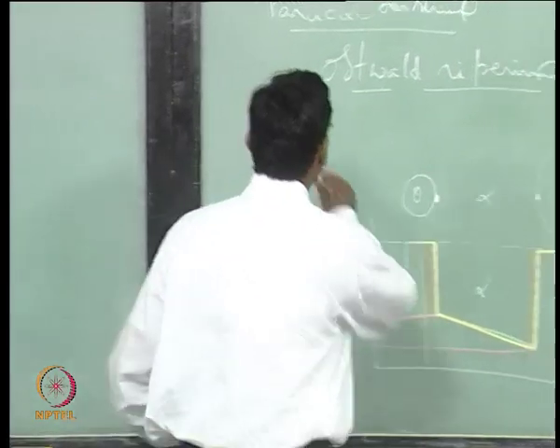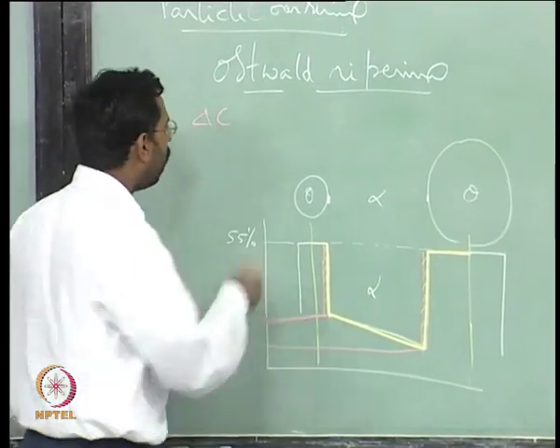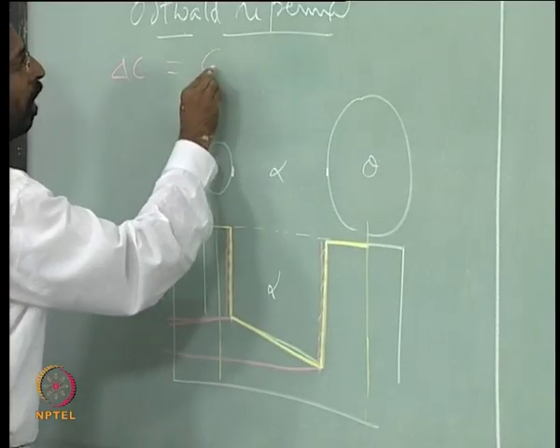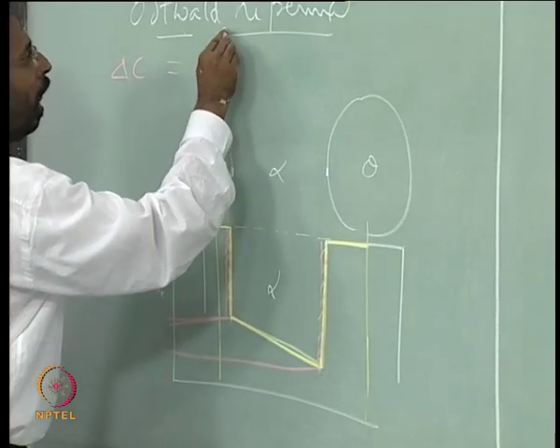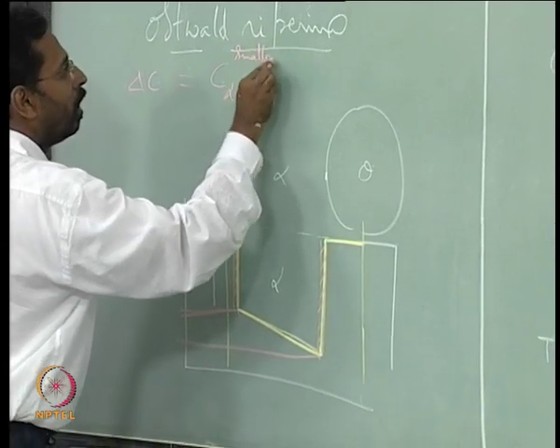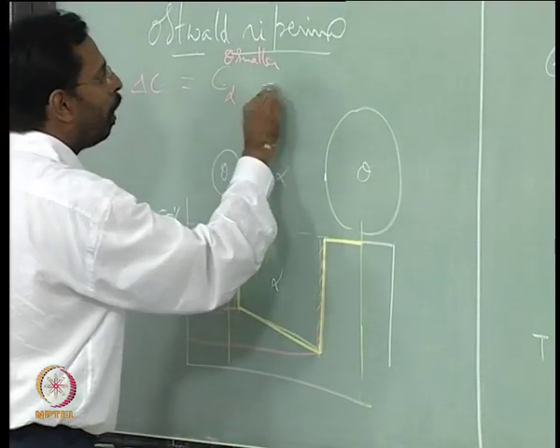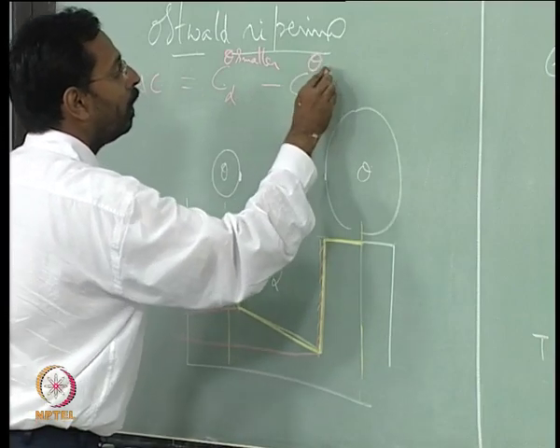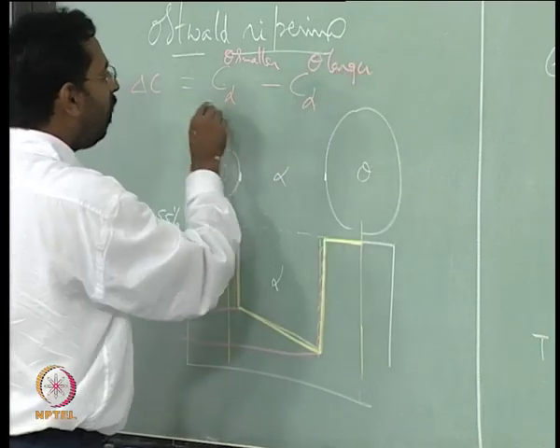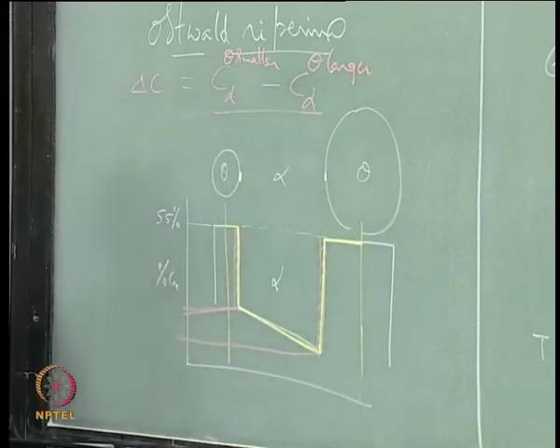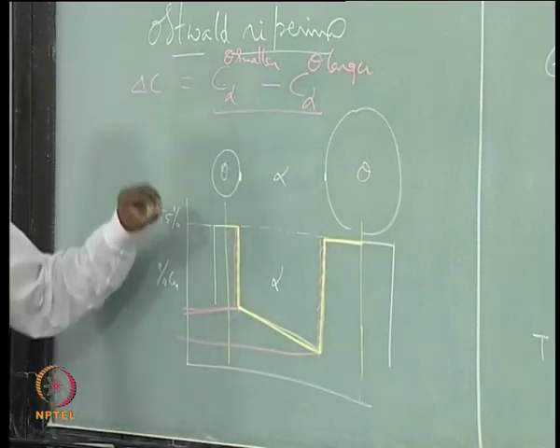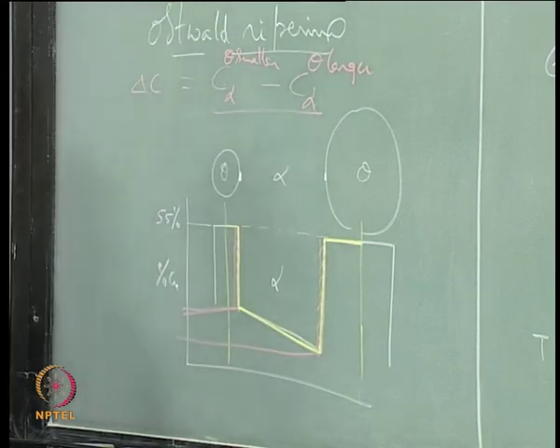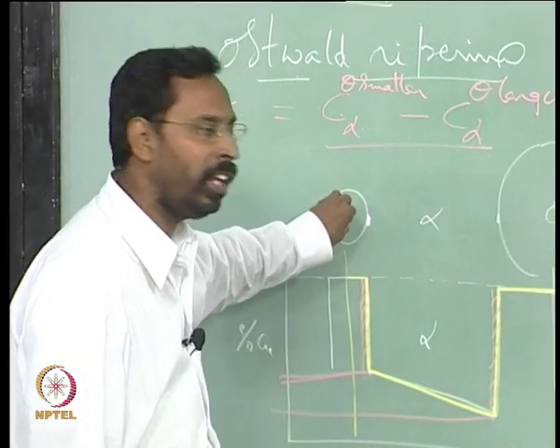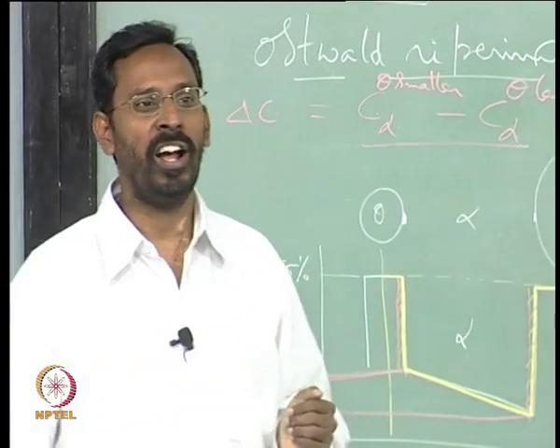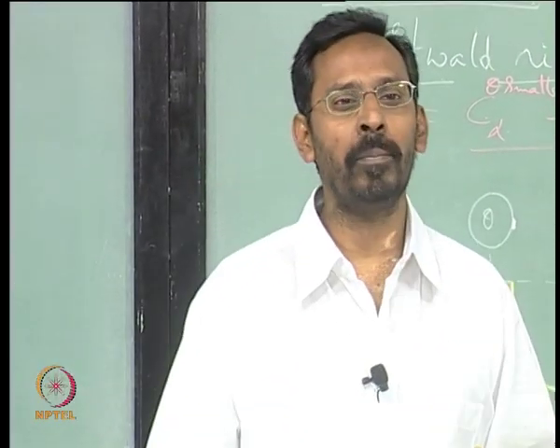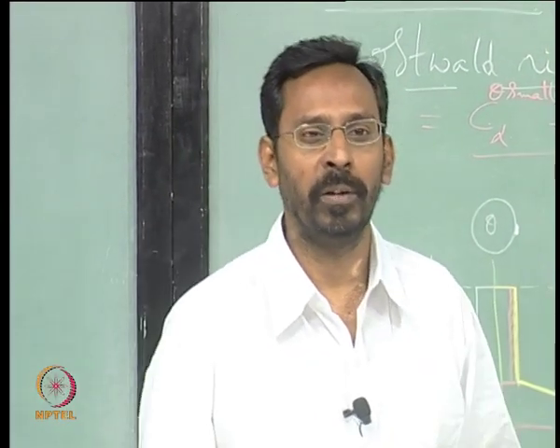because the dc by delta c, which is nothing but the composition of alpha in equilibrium with the smaller theta, minus the composition of alpha in equilibrium with the larger theta, this delta starts increasing as the smaller particles start becoming smaller and the larger particles start becoming larger. So, in the process, slowly the smaller particles will dissolve. At the expense of these smaller particles, the larger particles start growing.